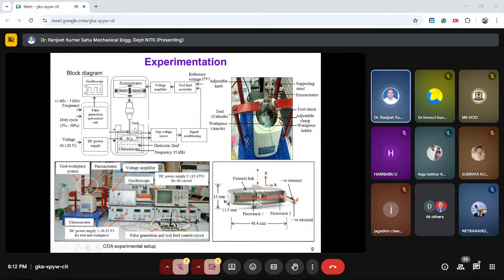See, this setup consists of a tool which is connected to the negative terminal of the DC power supply, and a workpiece connected to the positive terminal. This can be called a cathode, and this an anode. These two electrodes are separated by a small gap known as the inter-electrode gap, spark gap, or corona discharge gap, and they are immersed in a dielectric medium contained in an ultrasonicator. The ultrasonicator produces ultrasonic vibration at a certain frequency to avoid agglomeration of the particles and achieve uniform dispersion of the particles or debris produced in this dielectric medium.